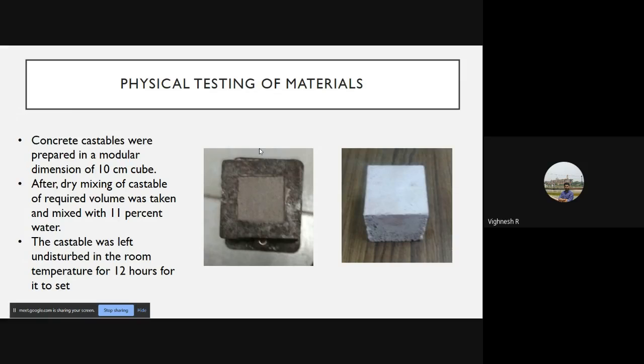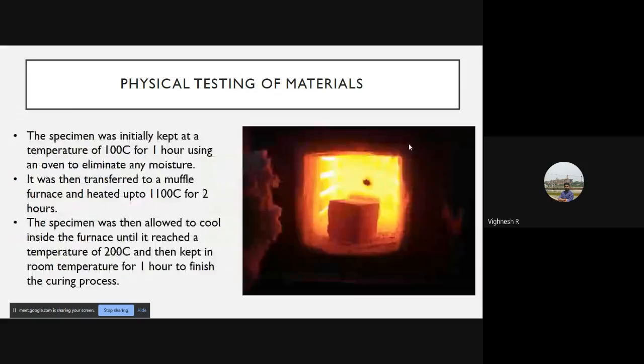The curing part was really different. As civil engineers, we usually cure structures using water. For refractory castables, we required heat. So this cube was kept inside this furnace, and the curing requires many steps. The first step was heating it to 100 degrees Celsius for 1 hour, then keeping it in a muffle furnace at 1100 degrees Celsius for about 2 hours, then at 200 degrees for an hour or so, and then keeping it at room temperature for 1 hour to finish the whole curing.